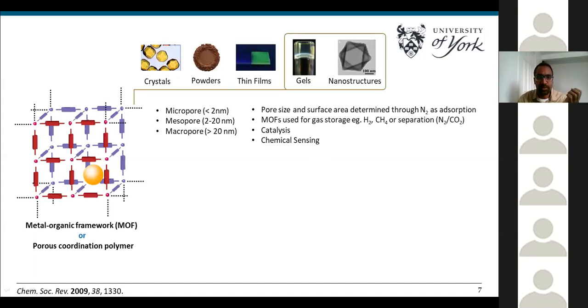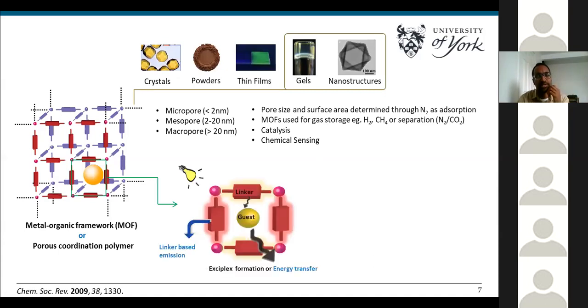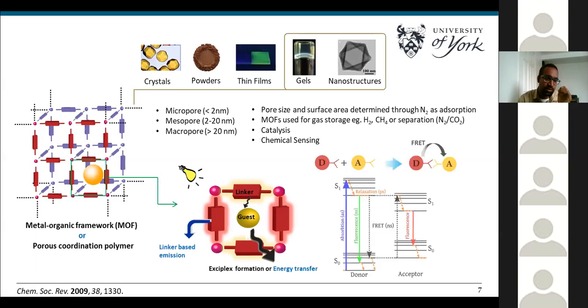light emission. So how do we achieve light emission in these materials? Since a MOF is an assembly of metal and organic linkers, if we choose an organic linker that is emissive, the whole MOF can be emissive due to linker-based emission when it is excited with light. Or if we incorporate an acceptor molecule or a guest molecule within the pores of the MOF, the energy from the linker can be transferred to the acceptor or guest molecule through a resonance energy transfer process. So we ultimately see a different emission, which is an acceptor emission.